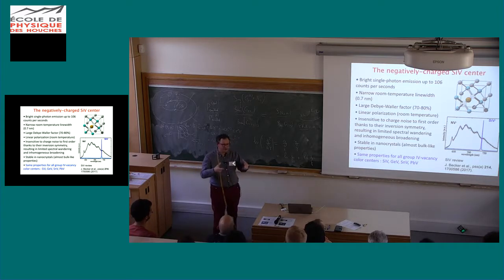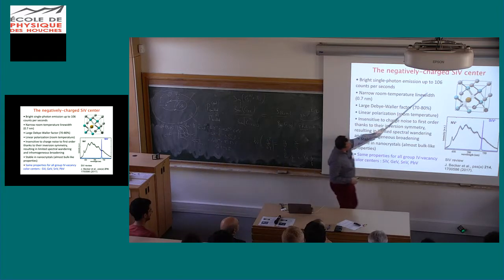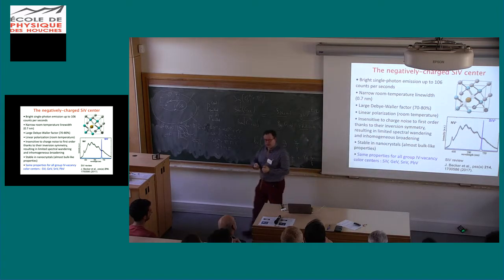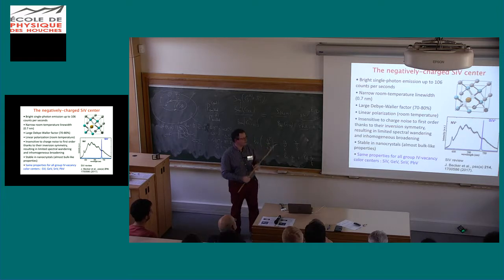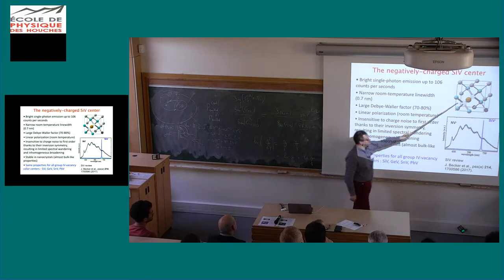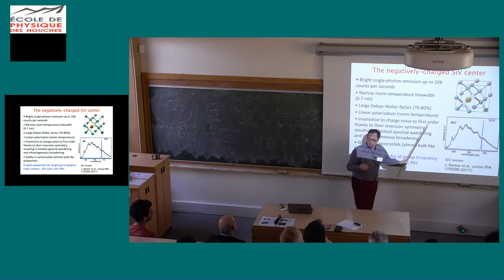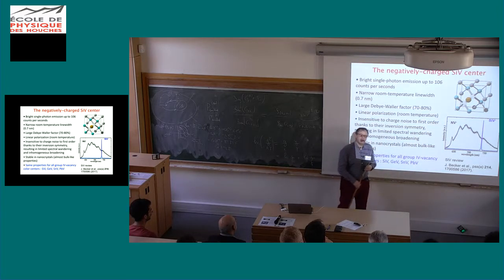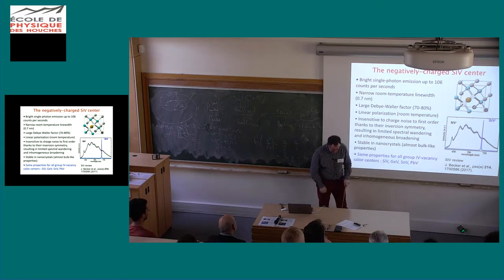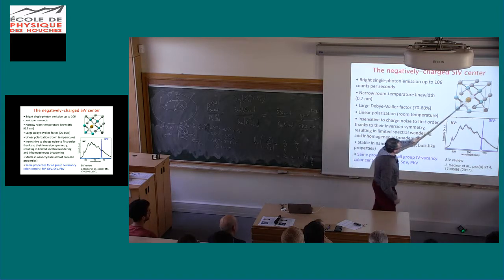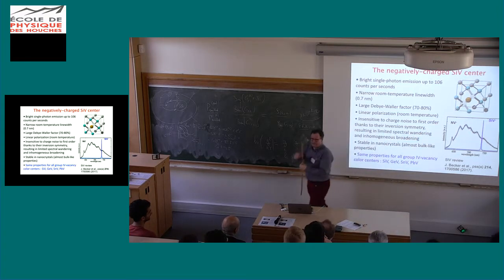It has rather open space between the atoms that are bonded. And so you can easily trap an impurity as an interstitial in the crystal. And this interstitial will then bond to two vacancies. So the structure of the silicon vacancy defect that has been really proven by EPR measurement consists of one interstitial silicon atom connected to two vacancies on the side of the crystal.